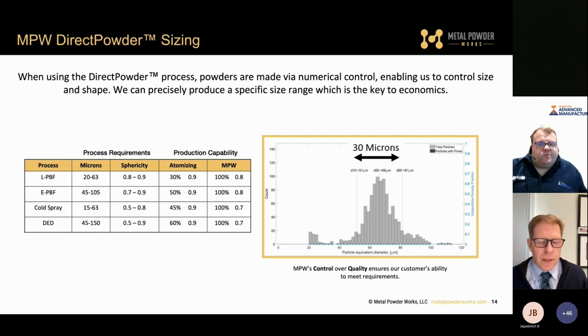I did a simple category here. Atomizing can typically produce a 0.9 sphericity, but the yield can be quite variable, from as little as 30% to as high as 60%, based on the process you might be going into. There are certain materials, titanium, Ti-64 being one of them, where there's only a need for powders in the 15 to 45, 20 to 63 range, which is about 40% of the yield, meaning we're lumping all of the cost of production on less than 50% of what we make. That's a commercial inhibition to titanium taking off as a material of choice.